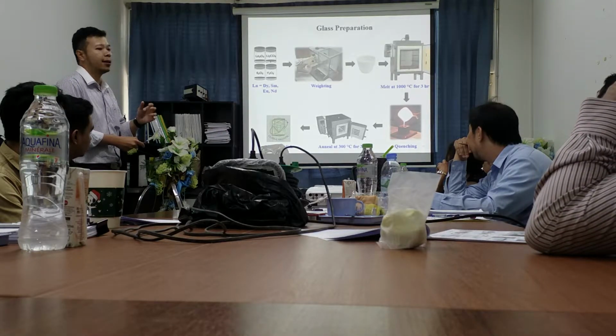Start from weighing, put it into the crucible, and then melt at 1000 degrees Celsius for 3 hours, and then quench it at room temperature, and anneal at 300 degrees Celsius for 3 hours, and finally we cut and polish to get the glass sample.